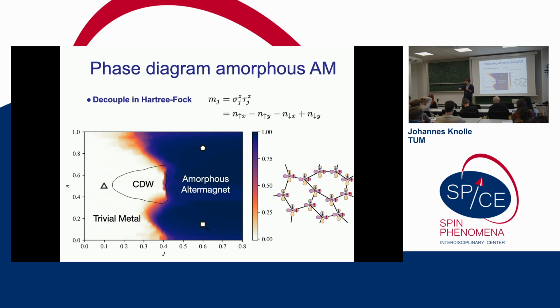Yeah, but then you lose this altermagnetism. Then you would lose some of the symmetries. But if we have chosen the hoppings, well, okay. So this is now details, yeah. If you basically chose the hoppings also to be fully symmetric, then it's true. Then it's a bit accidental when you choose that. Now, in principle, there is a kinetic energy, and that might, for example, turn the interaction Heisenberg-like. But if the hopping itself has an Ising-like anisotropy, then we always end up with this one.